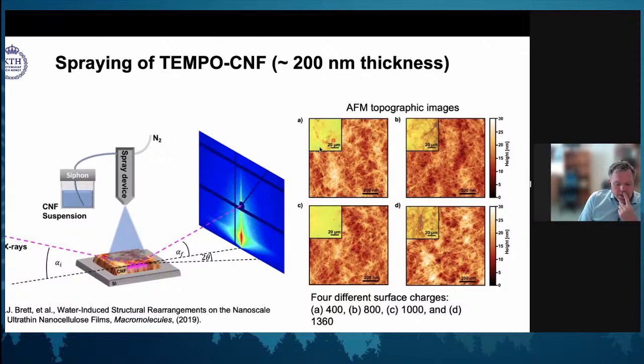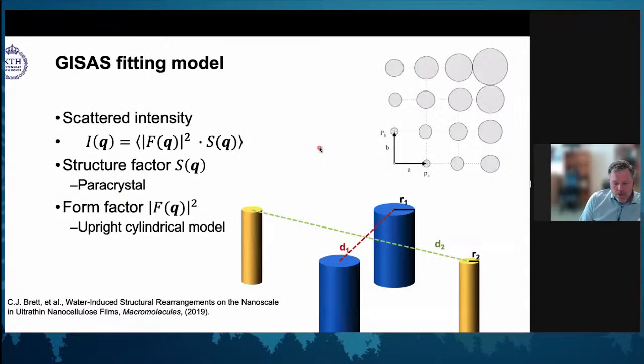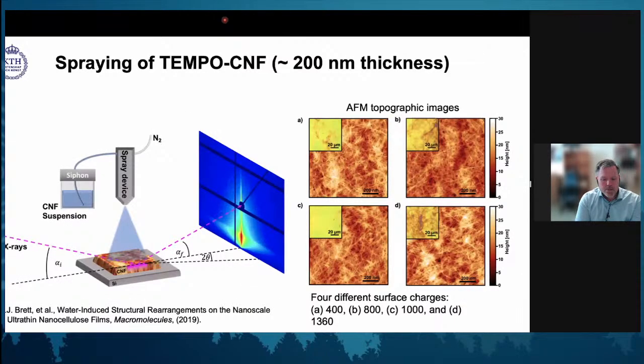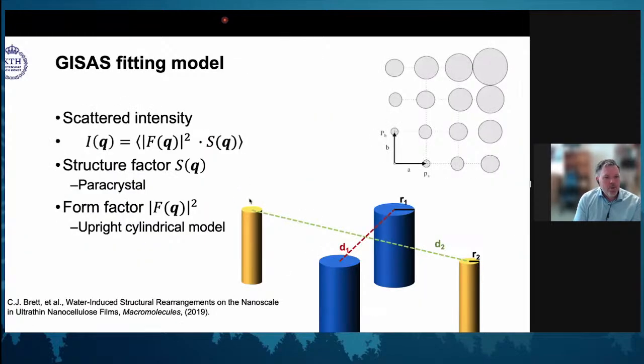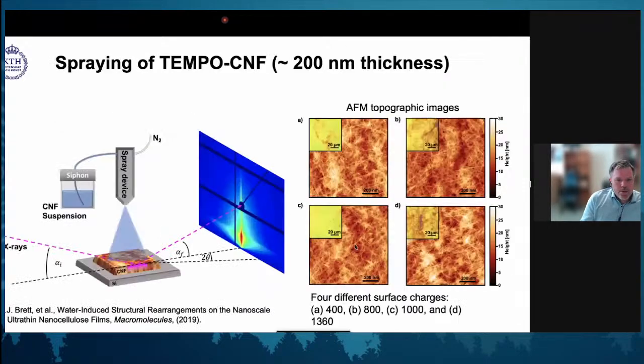But one of the possibilities with neutrons is that apart from characterizing structure, which you can do, you can characterize things with water. And when we want to characterize, one of the cool things and one of the problems is you need to find a fitting model to evaluate the structure. So starting with this system, we have films, we have some sort of structure. Let's pretend that we're all physicists for a moment. Let's assume that everything is simple, and then set up a model that is paracrystalline. It assumes that everything we see in the film, if you look at the film from the top, you can see a hole, or you can see fibers stacked together.